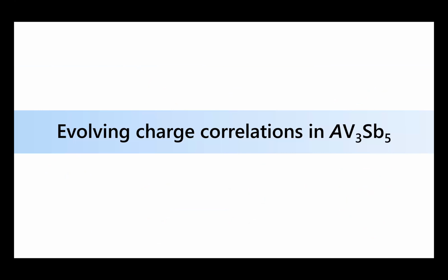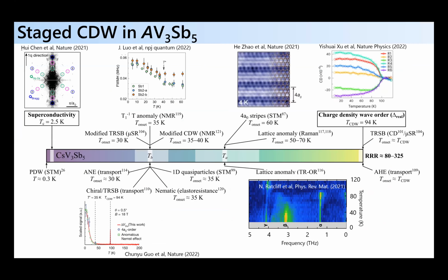Okay, so now as you cool from the charge density wave state down to the superconducting state, is there anything weird that goes on, or is it just simple one phase transition to another? And so, the answer is something rather complicated seems to be happening, and I don't have a good answer for exactly what's going on, except to show you this experimental phenomenology that shows you that there seems to be some crossover points in the material as you cool from the onset of charge density wave order all the way down to the superconducting state.